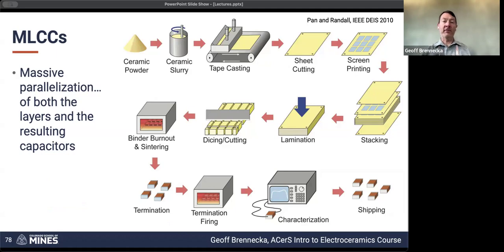So that termination is often done with a tin containing metallic paste of some sort. So it's often the same general chemistry as the electrode metal, whether that's silver or platinum or nickel or whatever, but then we'll also include some tin so that we can solder to that. Including a little bit of tin in the termination helps with soldering down the road significantly. So we've gone through this termination firing step, and it's generally going to be at a significantly lower temperature than the binder burnout and sintering.